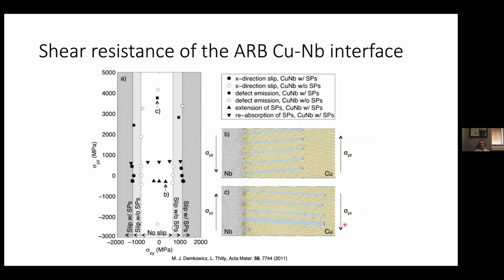Again, we did atomistic simulations to confirm that, and indeed it turns out that along the Burgers vector direction that is contained entirely within the interface plane, there's really very little in the way of shear resistance. So these symbols here indicate for you the location of the envelope for slip along the Burgers vector direction within the interface. And then along this direction, the horizontal direction here, you basically have no slip.